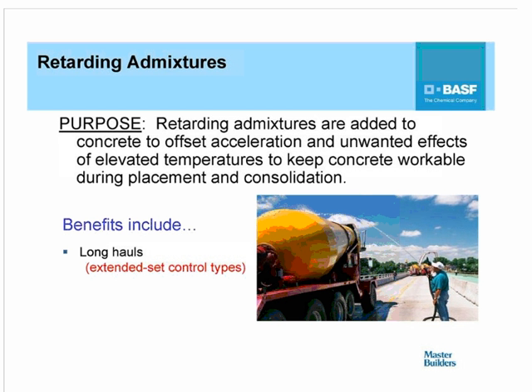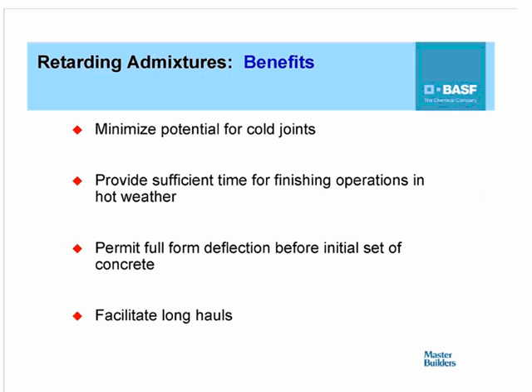Retarders are basically used to offset the acceleration that can occur under hot weather conditions. Some of the benefits also include long hauls, depending on the type that is used. When I talk about long hauls, I'm not necessarily referring to distance. It could be that even in an urban environment, due to traffic congestion, it takes a longer time for the concrete to be transported from the batch plant to the job site. The benefits of these retarding admixtures include minimizing the potential for cold joints, providing sufficient time for finishing operations in hot weather. In bridge deck application, they permit full form deflection before initial set of the concrete.